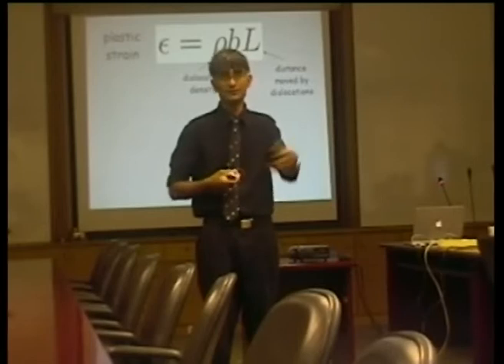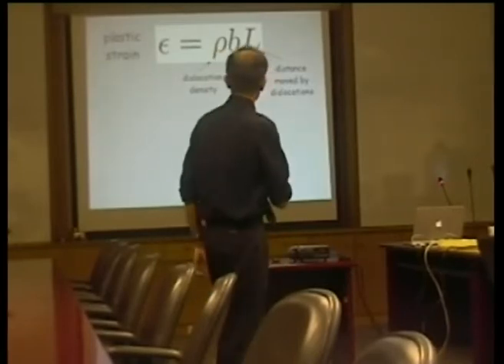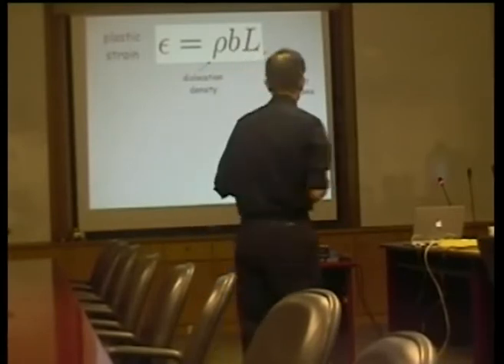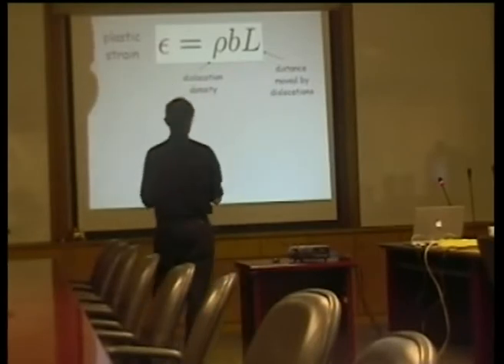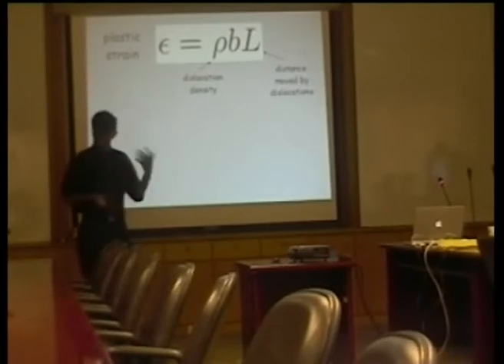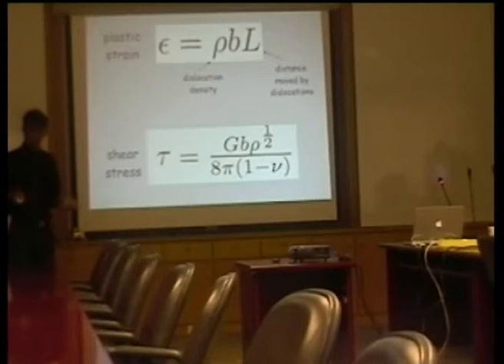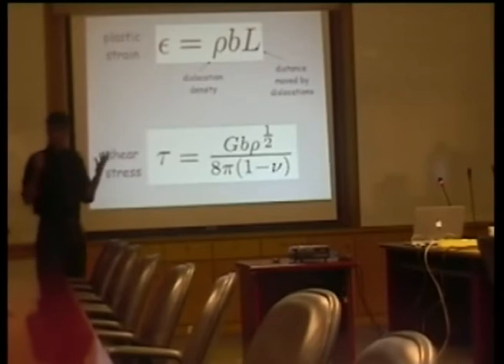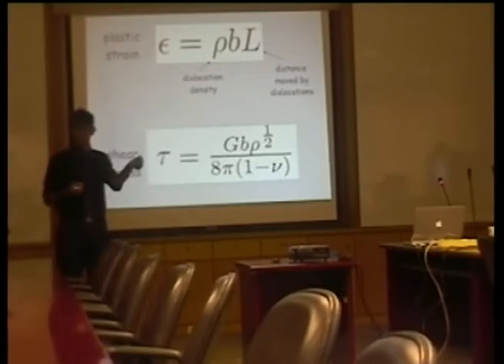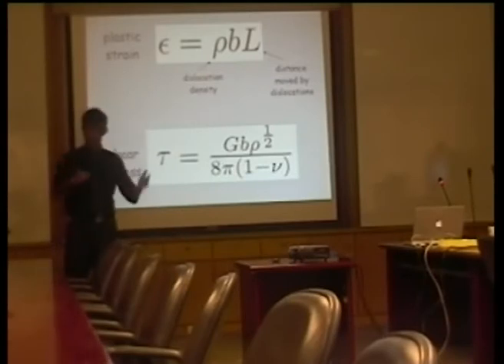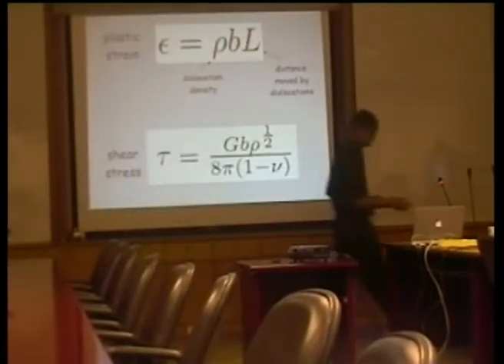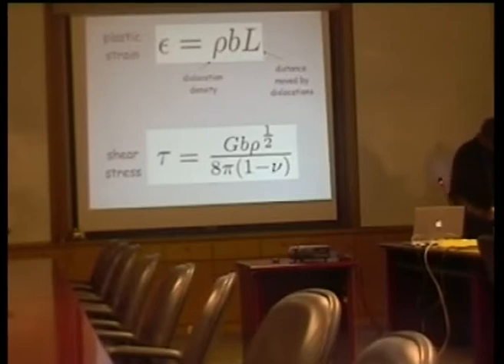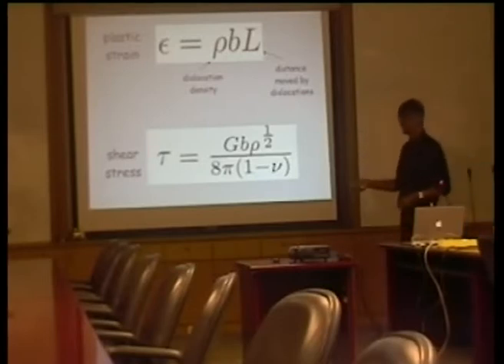Then if I apply a stress and the dislocations move a distance L, then the plastic strain will be epsilon. So this is just normal plasticity, where the strain that I expect, if I have that many dislocations, is the Burgers vector and the distance that they move by. Now, the shear stress that is required to move past a forest of dislocations, given this dislocation density, is related to the shear modulus G, the Burgers vector, and Poisson's ratio. So again, this is standard dislocation theory: if I have a dislocation density of rho, then I need a shear stress of that much to move past the dislocations. So this is the equation for plastic strain and that's for the stress.